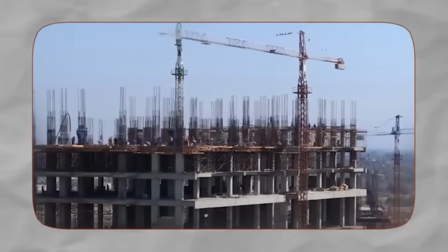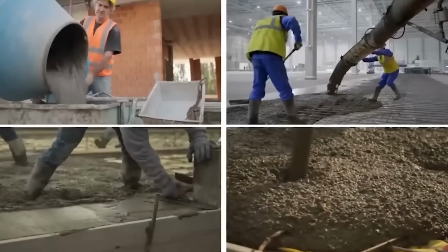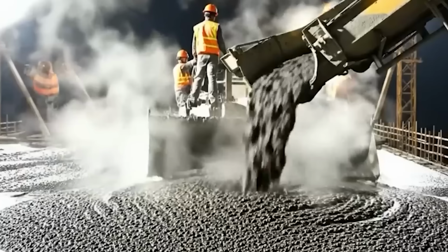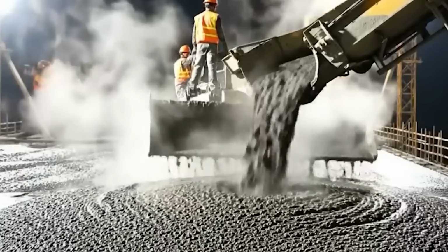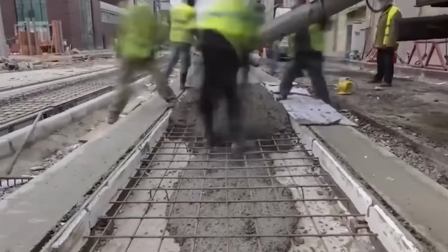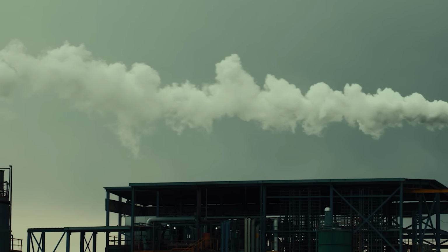Deliberately building a structural material around an ingredient known for batch-to-batch variability, rather than specifying it away, runs against almost every instinct in industrial materials engineering. And that is exactly why it does work. By precisely tuning the alkaline activator's concentration and the curing temperature and duration for each incoming batch of fly ash or slag, researchers could reliably produce geopolymer concrete. Meeting consistent structural benchmarks, regardless of which coal plant or steel mill the raw material originated from.